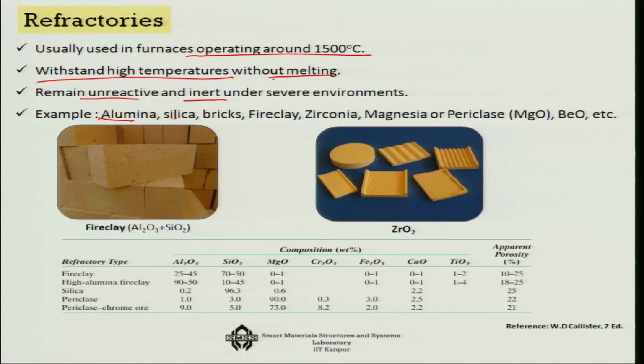There are many examples of them like alumina, silica based bricks, fire clay, zirconia, magnesia, or periclase. So, there is fire clay, which is a combination of alumina and silica, or there is zirconia. I will talk about zirconia later. If you look at it in terms of composition, suppose fire clay, you will see that most of it is actually alumina. More importantly, of course, silica is also there. In fact, silica is higher than alumina, and then magnesium oxide, a little bit of iron oxide, calcium oxide, and titanium dioxide. If you look at the high alumina fire clay, 90% is alumina, then 10 to 45 the silica may vary. Again, a little bit of magnesium oxide, iron oxide, and calcium oxide.